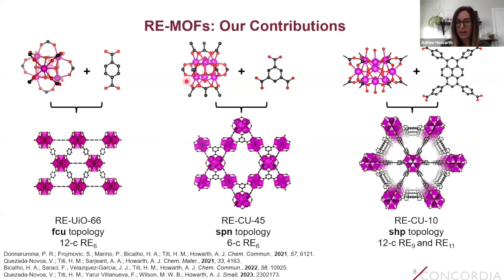This is a MOF that has 6 connected rare earth hexanuclear clusters bridged by the trimesic acid linker shown here, and has the overall SPN topology. And we call this MOF rare earth CU45, where CU stands for Concordia University.